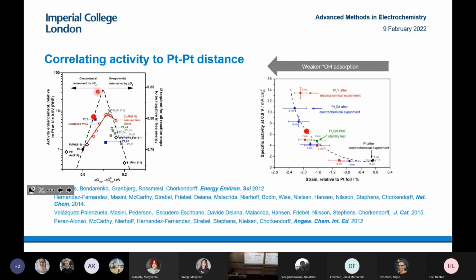We never saw we actually reached the peak of the volcano, but we did see that by changing the strain, we see activity. What's interesting about this is that the effect we actually got predicted from theory was actually wrong. This is many years' work of characterization of the actual platinum. We eventually found the reason why we think it was active. And there was a compressive strain effect, which is counterintuitive because we expect the rare earth to impose tensile strain.